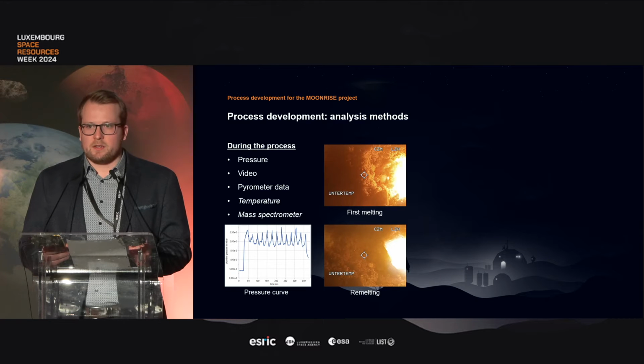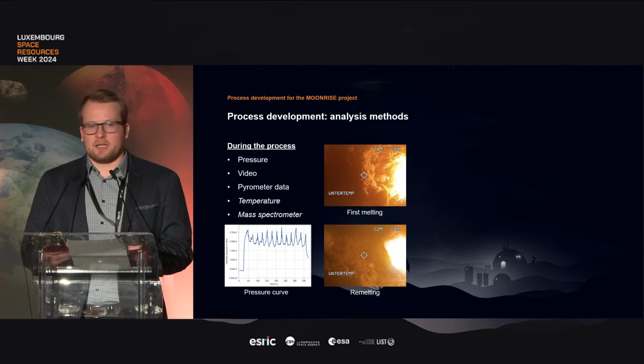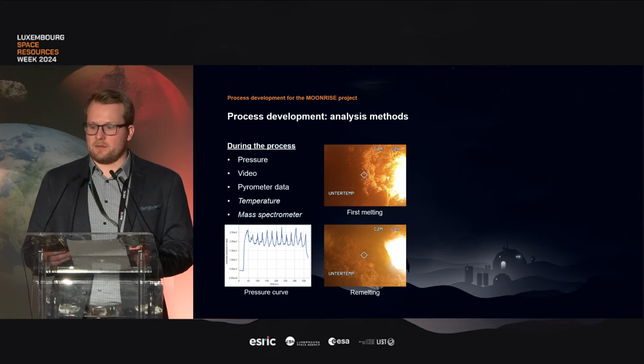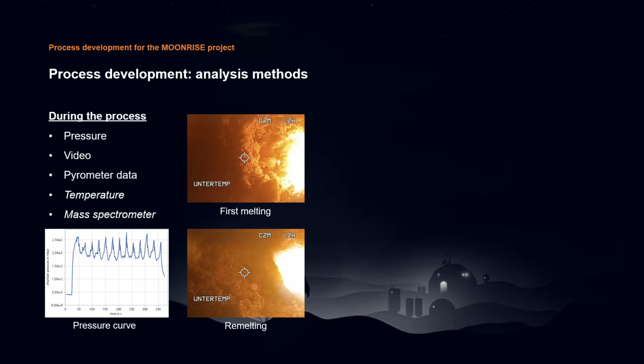But to determine all these parameter settings, we need some analyzing methods. And if we speak of analyzing methods, we differ between during-the-process methods and after-the-process methods. During the process, we measure the pressure in the chamber, which you can see on the bottom left diagram. There you can see that the pressure is increasing strongly when we melt the first loose regolith. And then when the laser turns off to jump to the start of the next vector, the pressure decreases and so on. And by the peaks in this graph, you can see how many vectors have been there. So it's 30.